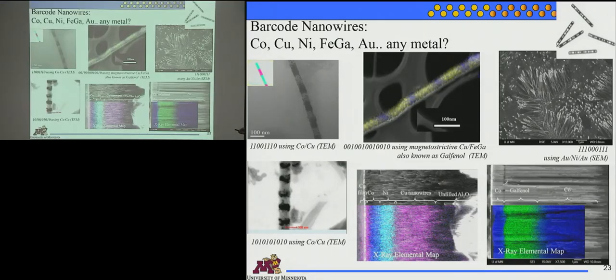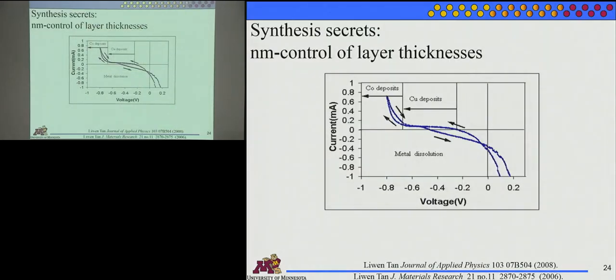And we can take them out of solution. Here they're still in the oxide. We just bent it and we're looking at the side. So they're all lined up. These blue layers are lots of nanowires going this way, just to check their uniformity. And we grow copper, gold, cobalt, nickel, iron, gallium, which is a magnetostrictive alloy, so it's very handy. And we sometimes call these nano-barcodes because we can grow so many different kinds, with a lot of different properties.